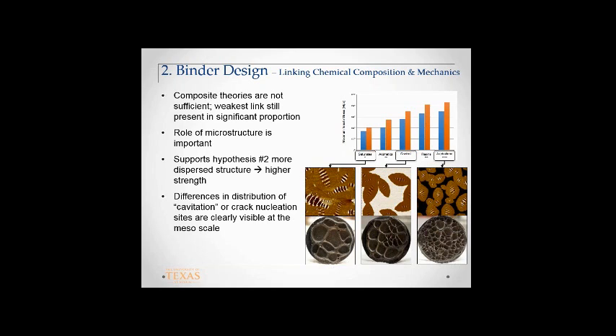This could also be a stiffness issue. Maybe this is just soft, so it has more cavities, nothing to do with asphaltene or saturates or anything. So we went back and actually tried to run this at higher rates of loading to artificially increase the stiffness, and it shows that that's not the case. So there are things we're working on to connect and understand where these cracks are born, how they grow, and what that has to do with the microstructure.